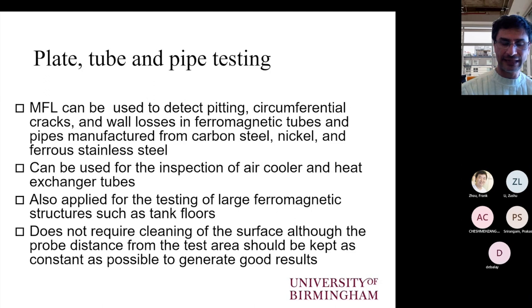So in that case, we can magnetize the entire thickness of the pipe, and we can again detect corrosion or erosion that may have affected the interior of the pipe. In the case of plates, it is quite common to use MFL for oil storage tanks in refineries. So it's one of the classic methods we use to assess these plates for corrosion and pitting corrosion specifically. And occasionally, we also use it for plates in ships. It is not a regular type of inspection, but occasionally, especially in tankers, it is one of the methods that is applied in order to rapidly assess the level of corrosion.